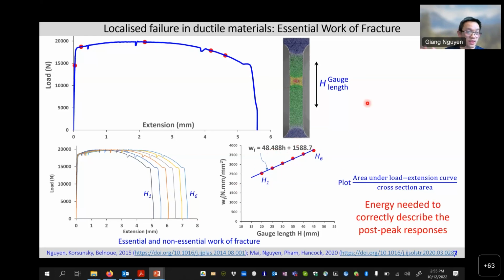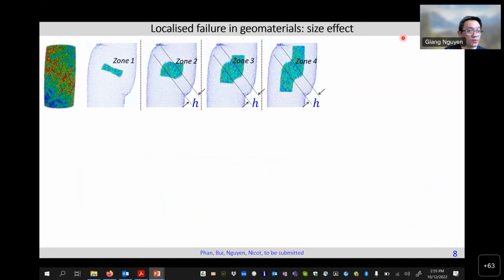So in this case, the conclusion here is that stress-strain relationships are not adequate. We need to add something else, and that something else in this case is energy dissipation, essential work of fracture. So now we go back to geomaterial. We use the same example, and we try to work out different zones, 1, 2, 3, 4, in this case, across the band. Here, we do the same thing.